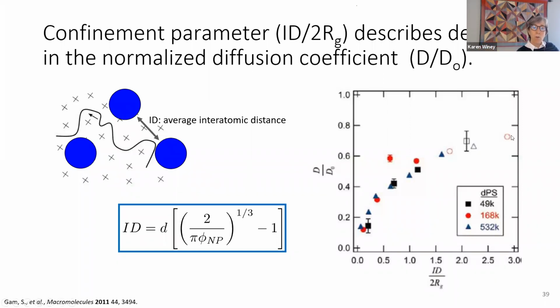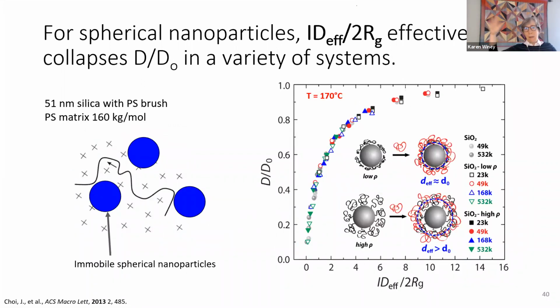You know, here the particles are 3 times the distance away from what RG is, and it's still making a substantial reduction in the diffusion, or the center of mass chain dynamics. And then many, many experiments later, this is a very powerful way of looking at this decrease in diffusion coefficient. What is captured in this summary plot are the bare particles, and then particles with low grafting density and particles with high grafting density.